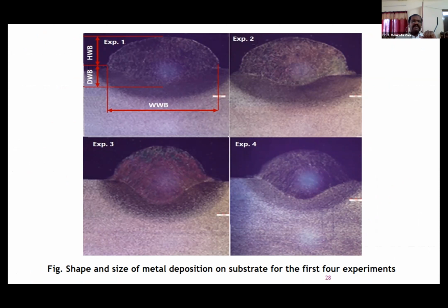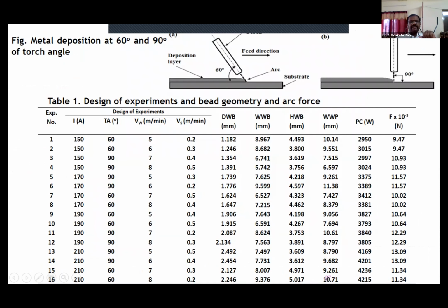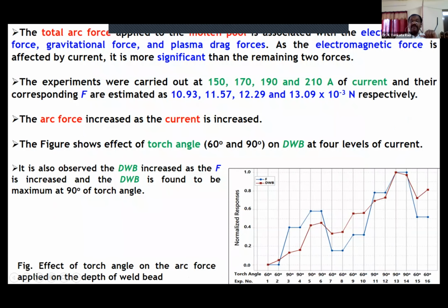In the design of experiments, we are increasing the amount of current. So here also in this figure, irrespective of the torch angle, the arc force is getting increased as the current is increased. But we are seeing the difference: at 60 degrees it is less, at 90 degrees the arc force is more. At the same time, the depth of the weld bead is also found more when the arc force is increased. So that is the effect of arc force on the depth of the weld bead. When the depth of the weld bead is more, definitely the width will be more and the height is reduced. That is not our requirement. When you are able to reduce the arc force, then the depth will be reduced, the width is also reduced, and the height of the weld bead is increased. That is our aim.